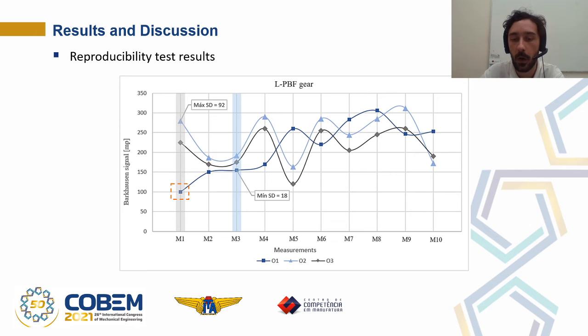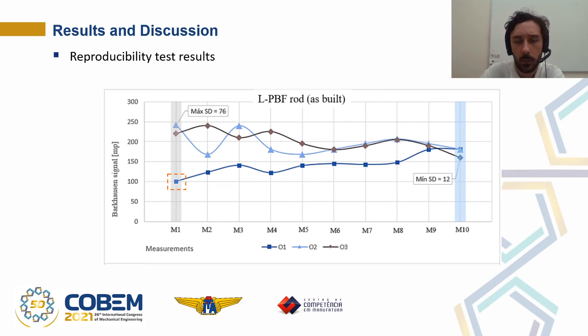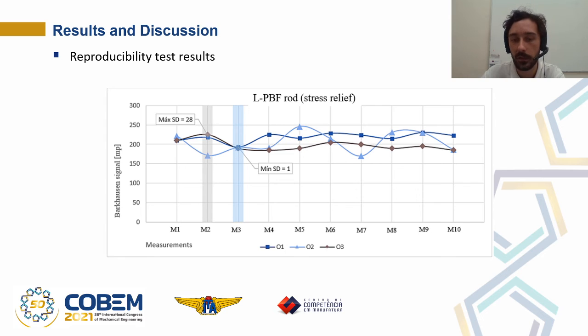The maximum value of the standard deviation for the gear sample is 92, and the minimum value is 18. For the first rod sample, it can be seen that there is a divergence in the first measurement for one of the operators, and the maximum value of the standard deviation is 76, and the minimum is 12. For the second rod sample, the minimum standard deviation is 1, and the maximum is 28, showing that the surface geometry is a very important parameter when evaluating the statistical variation of the Barkhausen signal.